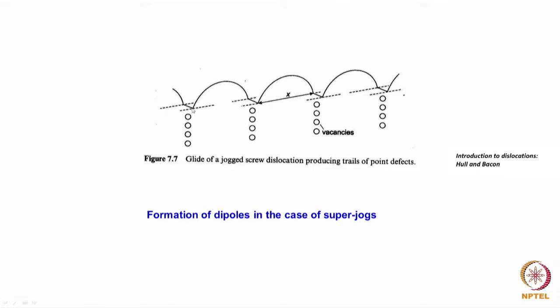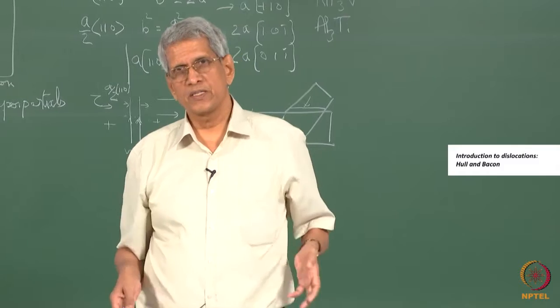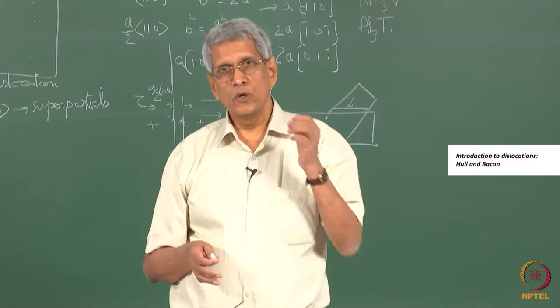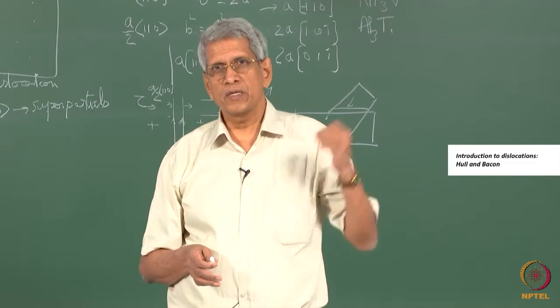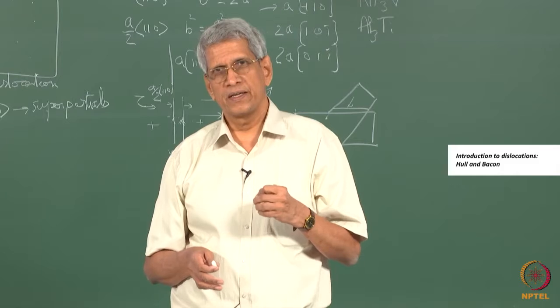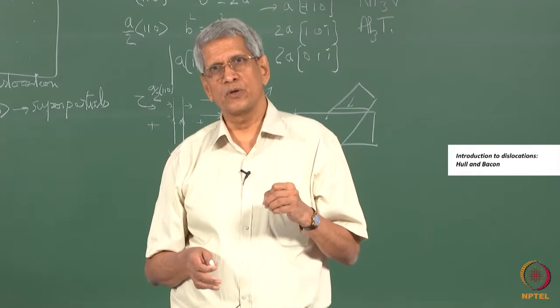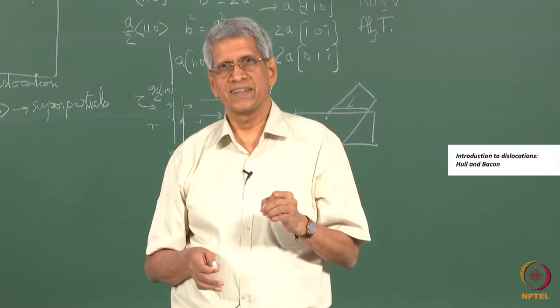That means that a screw dislocation, when they interact, they create a jog. For the jog to move, we require a very high stress. Though the increase in segment of the dislocation line is very small, the stress which is required to make this dislocation move is very high. So the jogs have an important role to decide the strength of the material.